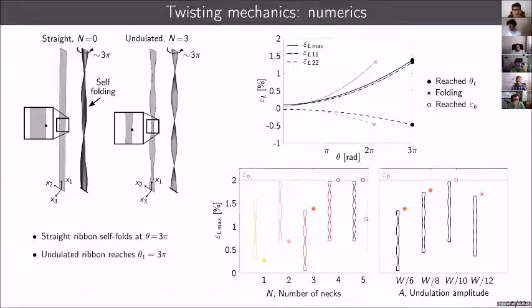We also tried to change the undulation amplitude. And what you can see over here is that by decreasing the undulation amplitude, towards the right, we increase the maximum principal strain. And in particular, as we decrease the undulation amplitude and the ribbon becomes very similar to the straight one, we also have self-folding. So for this configuration of it. So based on this analysis, for the rest of the presentation, we decided to go ahead with three necks and a certain width of W divided by six, a certain undulation amplitude of W divided by six.